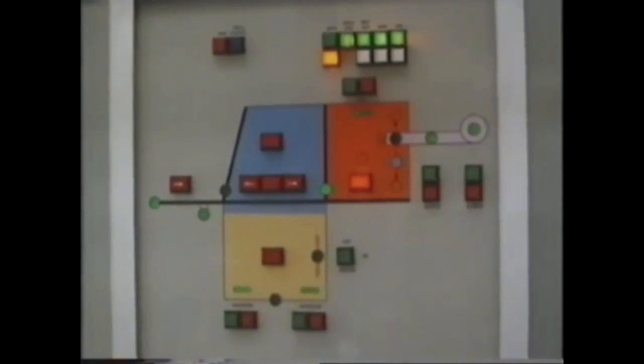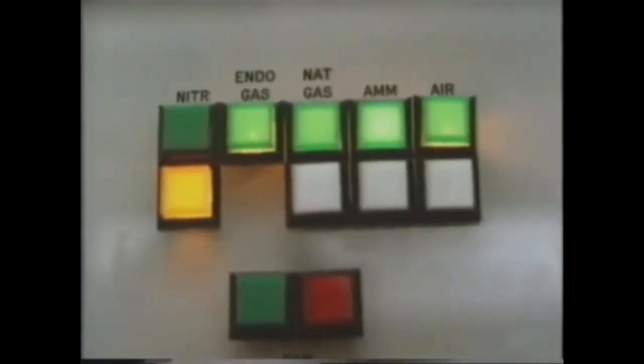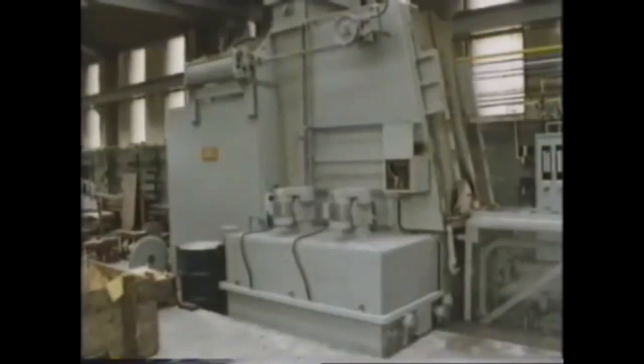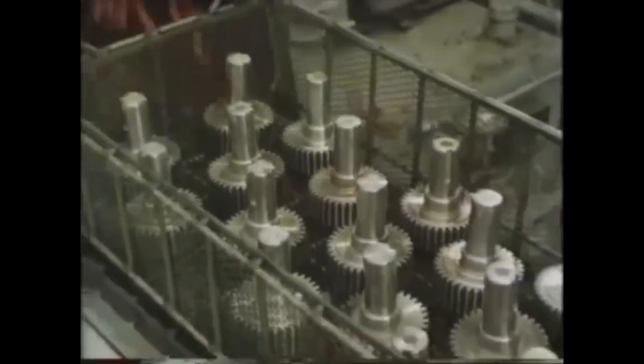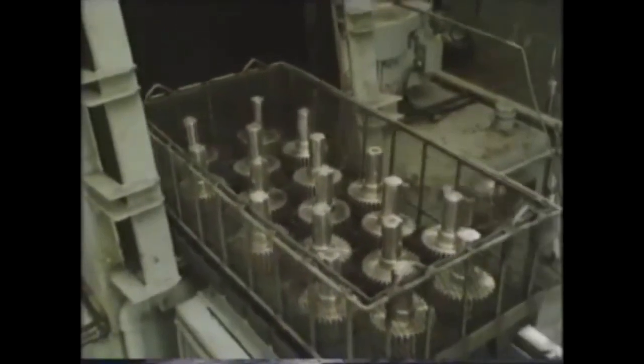The method to be used here is called gas carburizing. In essence, the parts are placed in a furnace, heated to the required temperature, and a carbon-rich gas introduced. Again, the depth of the case will depend on the temperature of the furnace and the time the piece is left there. The equipment is in 3 parts: an oil quench tank, an outer compartment or vestibule, and an inner furnace. The inner furnace for the gear shafts is at a temperature of 900 degrees centigrade, and it's here that the carburizing will take place. The gear shafts are cleaned, degreased, and loaded in a wire basket, and this is pulled on rollers into the outer vestibule.